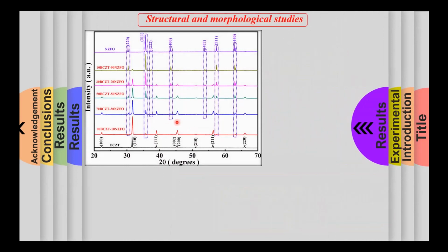In the X-ray diffraction profiles, two sets of peaks were identified. One set corresponds to the piezoelectric phase, while the other, the ones which I have shown in the dotted box, correspond to the magnetic nickel zinc ferrite phase. And no impurity phase was detected, which implies that no chemical reaction took place between the constituent phases. We also see that the intensity of the peaks of the magnetic phase keeps on increasing as we increase the weight fraction of the nickel zinc ferrite.